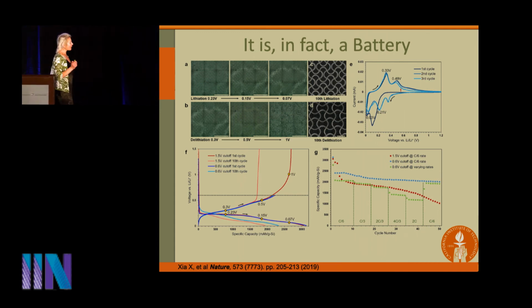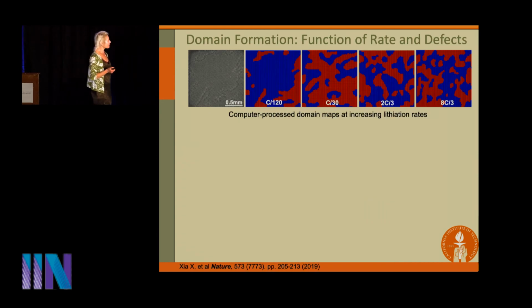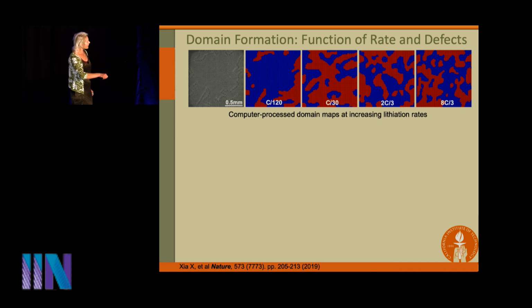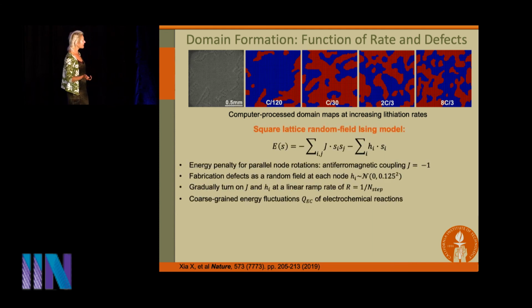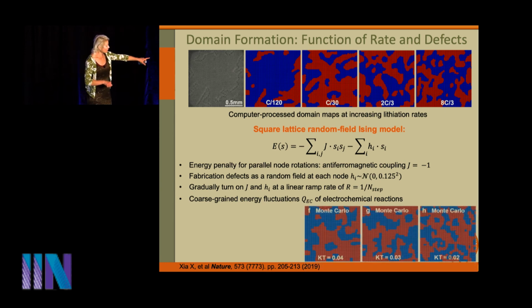So looking at these electrochemical properties, we realize that actually changing the rate at which we lithiate them gives rise to different domain formations. And so these are all SEM images. These are not computer simulated. These are actual SEM images of some of the different patterns that form. Well, why do these patterns form? Well, it turns out it's all about the defects. And actually, we can use this antiferromagnetic type Ising model to describe the coupling of these domain formations within these networks. And so we were able to simulate, to put the theoretical framework over this.